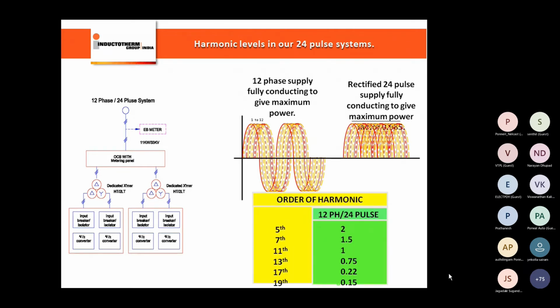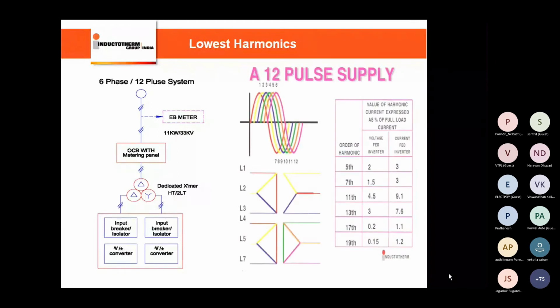What we are talking about in our Inductotherm 24 pulse designs, in terms of total harmonic distortion, is typically less than 6% on the current, and the voltage is less than about 5% or 4%. Individual voltages are even less than 3% or 2%. They are much safer and in line with the norms. Coming to the 12 pulse systems, the harmonics are about 7 to 7.5%, or near 8%. Still, with our 12 pulse designs, our harmonics are well within the TANGEDCO norms or on the border.